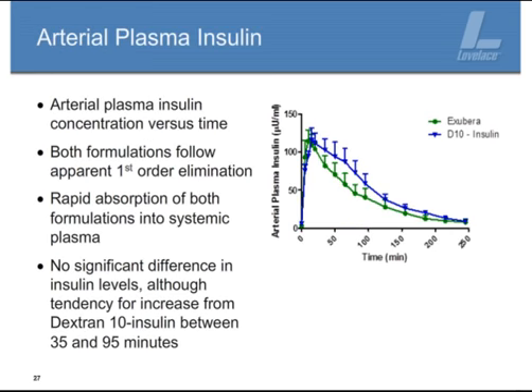Because of that, we're then able to look at this graph on the right, which is the arterial plasma concentration of insulin for each formulation as a function of time. You can see both of these follow apparent first-order elimination. More importantly, you see how quickly the material was absorbed into the systemic plasma, and how the Cmax and the Tmax for both appear to be very, very close. We'll get through some of the modeling in a little bit.